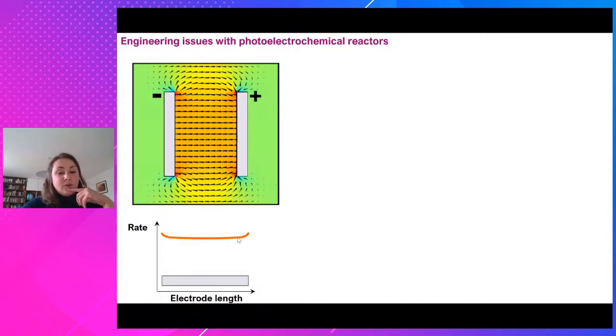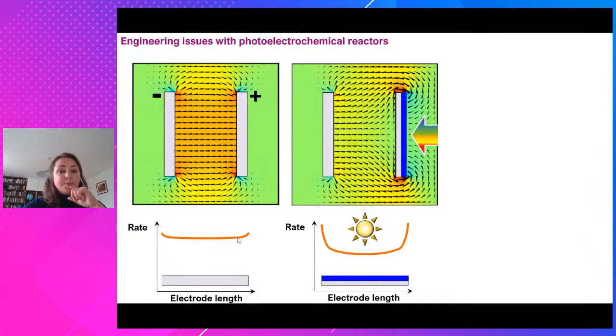Now, because in photoelectrochemical reactors you have to get the light in, you're then constrained to either using transparent substrates, which sometimes are too resistive for scale-up, or you reorientate one of the electrodes so that the surface that absorbs the light is actually facing towards the outside of the reactor instead of facing the other electrode. So now you have a very non-uniform distribution of the electric field.